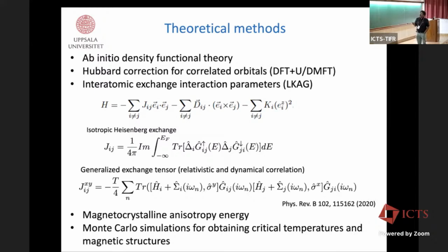So basically a Heisenberg spin model can have these kinds of terms. Actually, this is an isotropic term. This is an antisymmetric Dzyaloshinskii-Moriya interaction. This is the magnetic anisotropy, single ion magnetic anisotropy. If you wish, you can add more terms in the spin Hamiltonian. And the good thing is that with our technologies, we can calculate the parameters of these terms in the Hamiltonian. That gives us an authenticity in the material's properties. All these are calculated on the basis of Green's function with a multiple scattering approach and things like that.